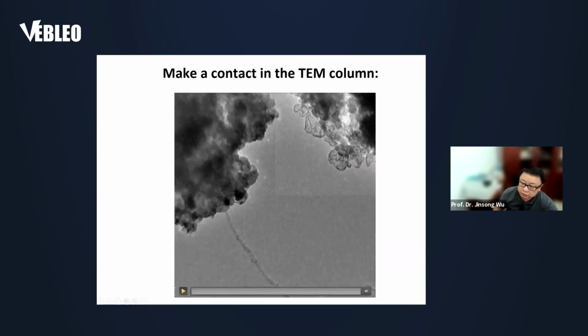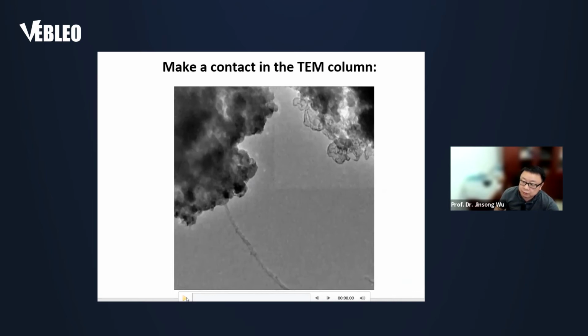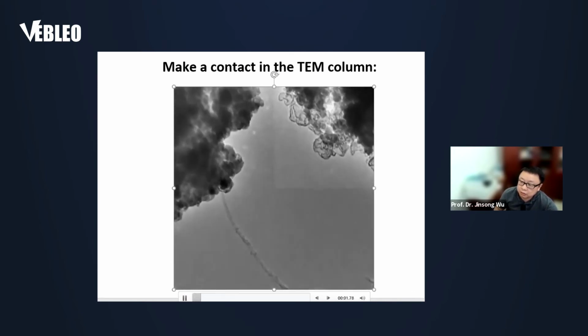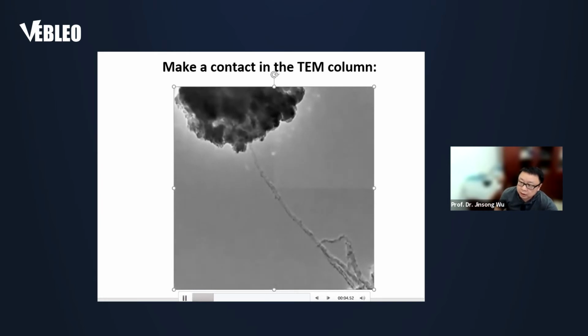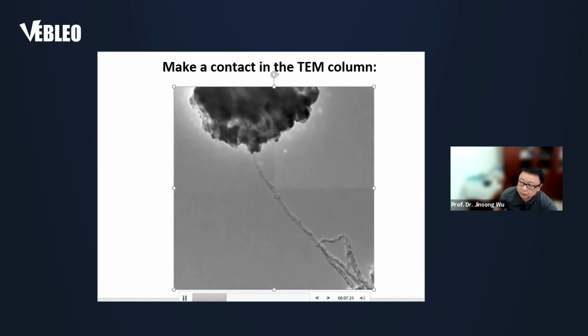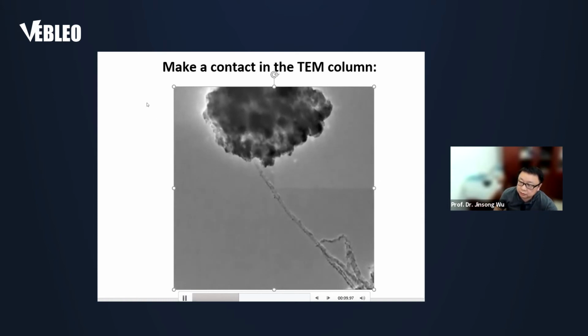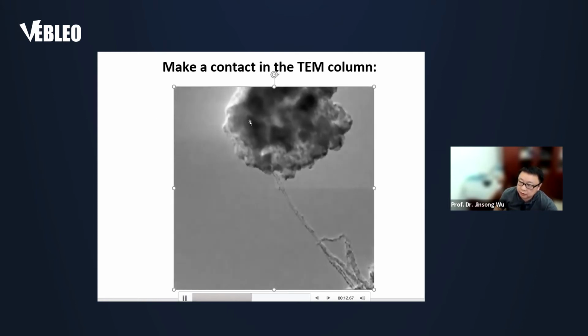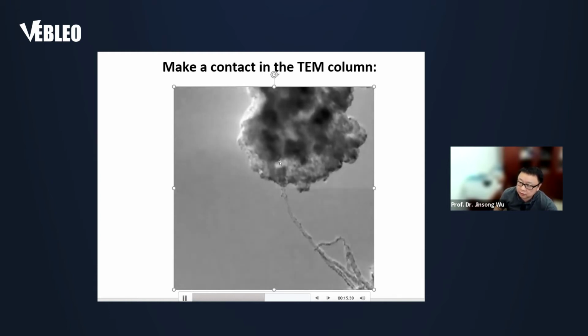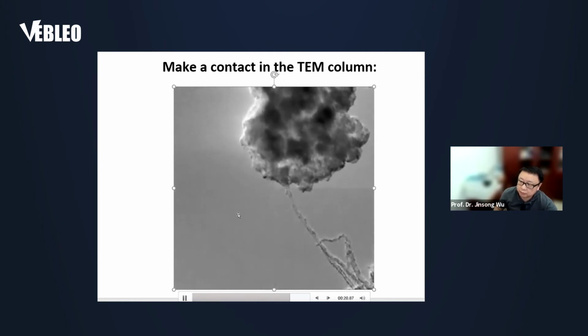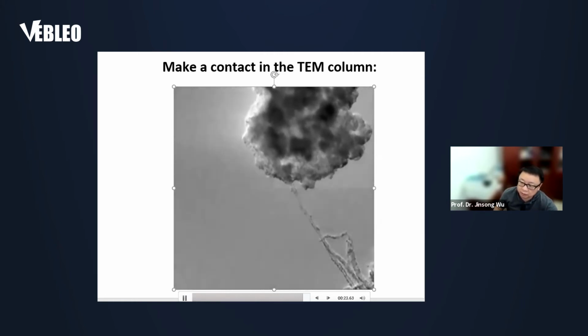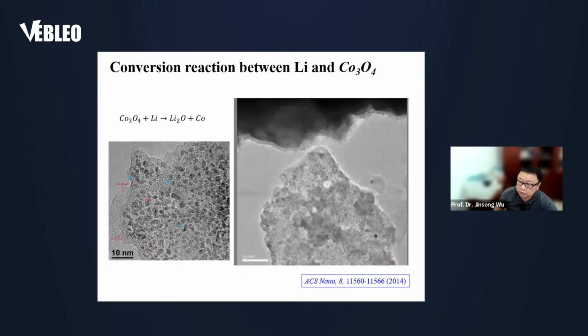This video shows how we can assemble a miniature battery inside the TEM column. You see here's a tungsten tip loaded with lithium, covered with lithium oxide, and here's a carbon nanotube. Once we make a contact, a miniature battery is built inside the TEM column. And after that, we can do the lithiation.